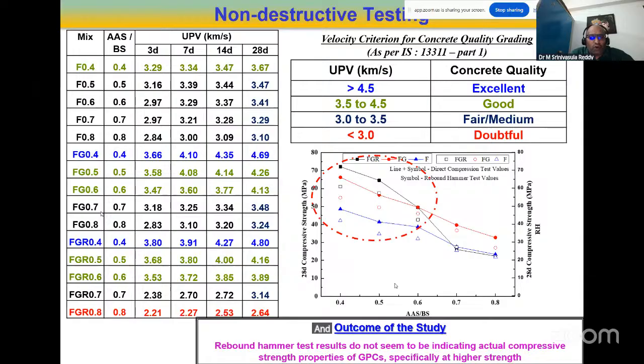And I found that only for lower AS to BS ratio concretes, like 0.4, I noticed the concrete quality is excellent, based on the ultrasonic pulse velocity. I found it is more than 4.5, and we can observe here that for the 0.4 ratio, only the GGBS and the fly ash, GGBS, red mud combinations are showing excellent concrete. But overall we can say, except for fly ash, GGBS and red mud at the 0.8 ratio, all are showing fair to excellent quality concrete.